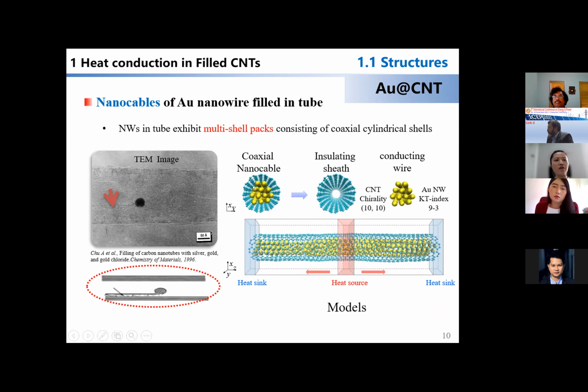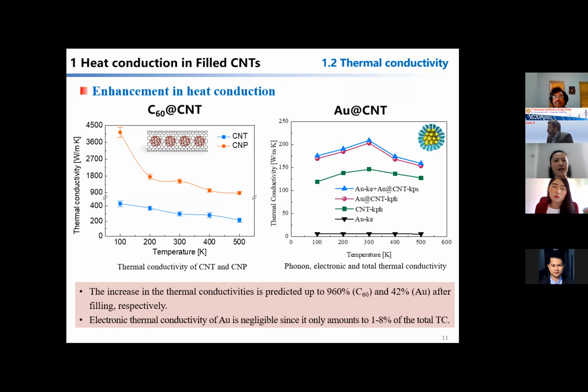Based on these two models, carbon nano-peapods and nanocables, we employed molecular dynamics to calculate thermal conductivity. The results show that the filled carbon-60 can increase thermal conductivity up to 9.6 times, a huge enhancement. The filled nanowire can also increase the thermal conductivity, though not as much as carbon-60 filling, because gold and carbon are heterogeneous atoms.